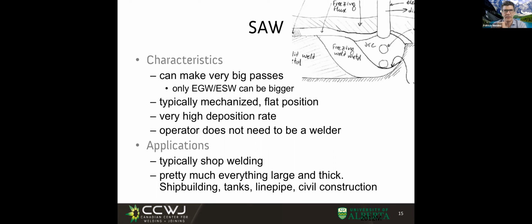In submerged arc welding, if the arc length is too short, you know it because the voltage would be low, and then what you do is slow down the wire feed speed. If the arc length is too long, you'd see a voltage that is too high, and then you increase the wire feed speed. Okay, so does the operator manually do that? No, it's automatic.